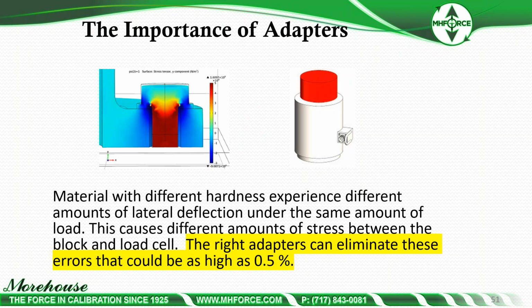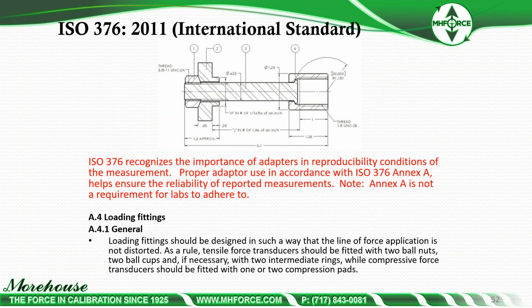ISO is going to recommend top adapters. Just general good practice is to have a top adapter for that load cell, and that's what's in red up here. So have a top adapter that's sent in with that cell, and then have it calibrated with that, because you're going to harden that material. If it's soft material, over the lifespan of it, you're going to harden it. It should stay with the load cell. Our preferred, if we're making a top block, we're sending it out to be heat treated to give better safety factors, and it makes the results much more reproducible as far as rotation. We get much better numbers if we use a hardened adapter on the top of the load cell.